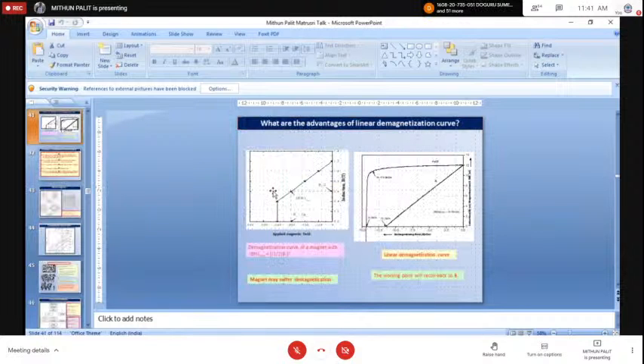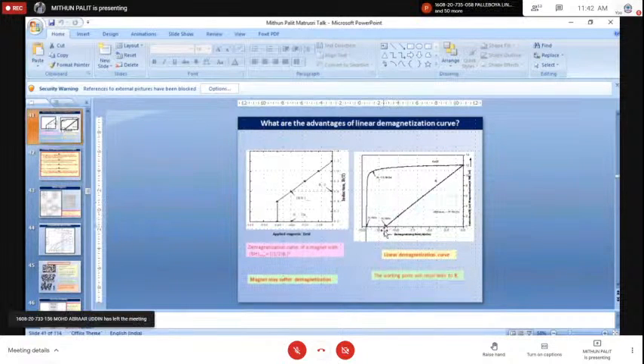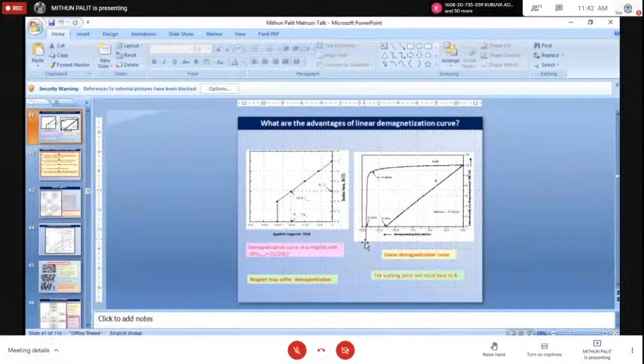Well, now as we are always talking about the second quadrant curve, you can see that the one in the shape of a square, which is at the top, is the M versus H curve, and the sloping line shown inside is called the B versus H plot. Now, if the coercivity of the magnet is very low, then this straight line will not remain straight up to where it cuts the horizontal axis. Instead, if you see the left side picture, there will be some slope. The linear plot will slope down towards the edge, and then cut the horizontal axis. So if the scenario is like the left side case, then what happens? We don't call this a good magnet, because with every cycle of demagnetization, this magnet will lose its own magnetic strength.